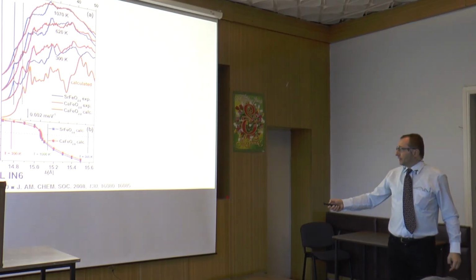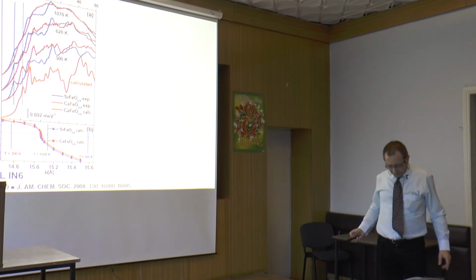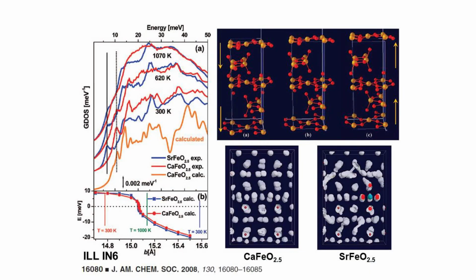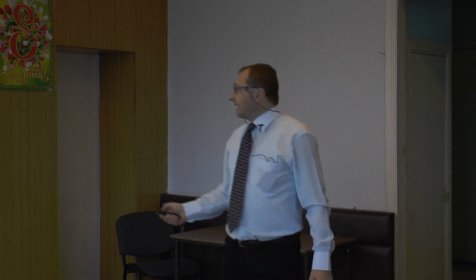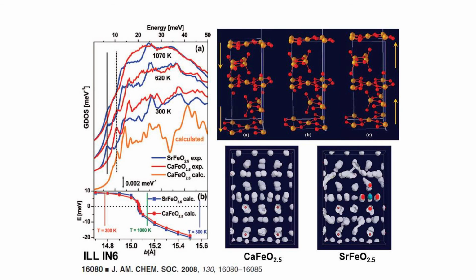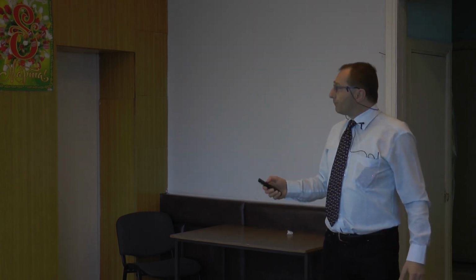While this is the position of the lattice parameter at room temperature of our oxygen conducting systems. And here it has not a true minimum, because it means that it can go up and down. And again, if we make diffraction on the calcium iron at 1000 Kelvin, we see that the thermal expansion makes the lattice parameter increase, and here we have conduction again. Okay, so this is ab initio molecular dynamics, and we see the vibration of the tetrahedral oxygen in calcium iron. We see that we have thermal vibration, but all these vibrations are around the stable position. Conversely, in strontium iron, we see that we have migration from one position to the other. So I think these experiments combined with the theory have allowed us to understand what happens.